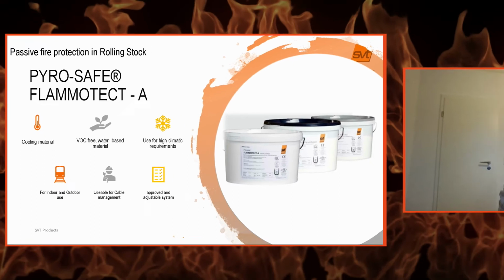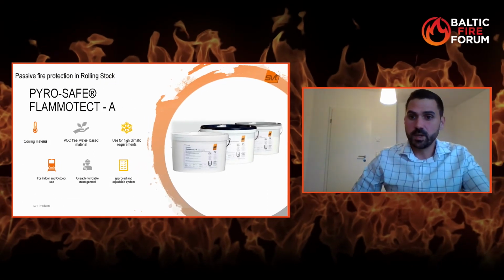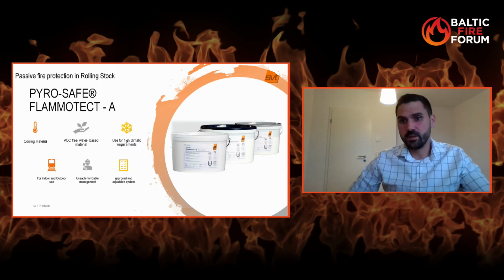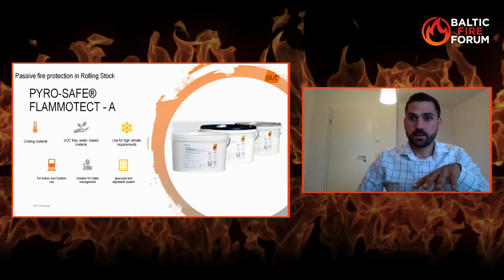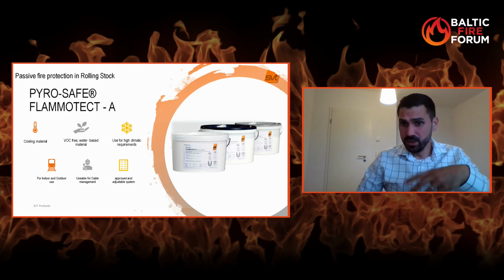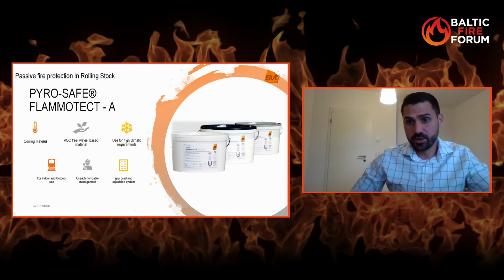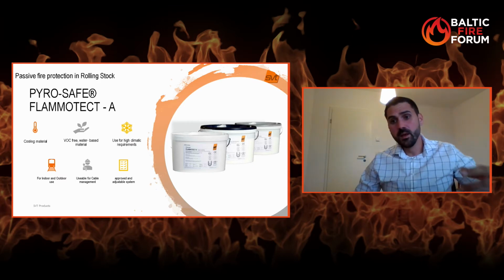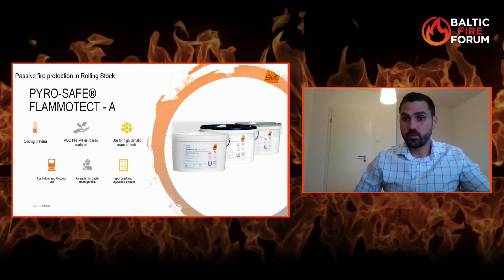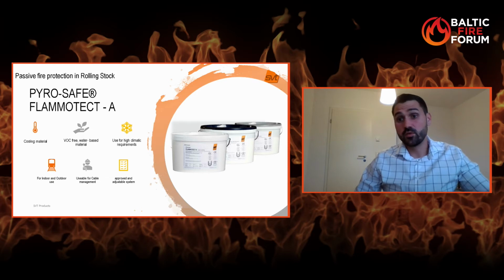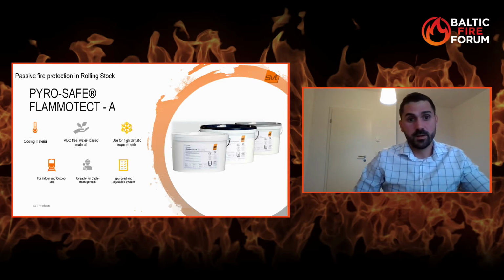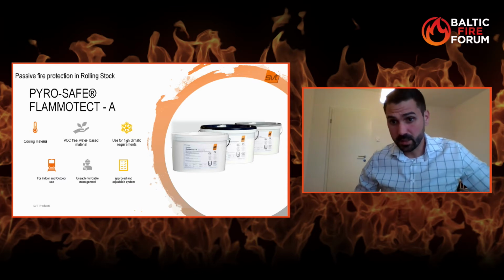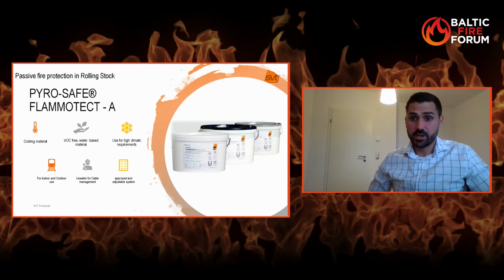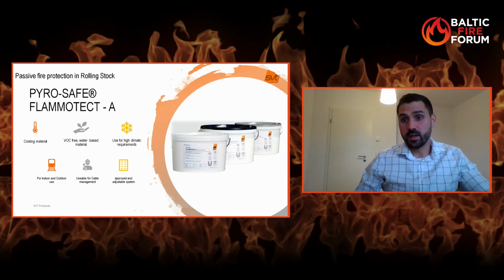This product here, as I told you before, we have some intumescent coatings or intumescent materials, but we also have some cooling materials. This coating is a cooling material, so it's ablative, it's endothermic. You can use it to cool down the substrate. It reacts at a temperature of approximately 200 degrees and has bonded water inside, and releases this bonded water and cools down the system or the construction. So it's one of our oldest materials. It's been over 20 years now in service, and it's really good for cooling down the substrates.